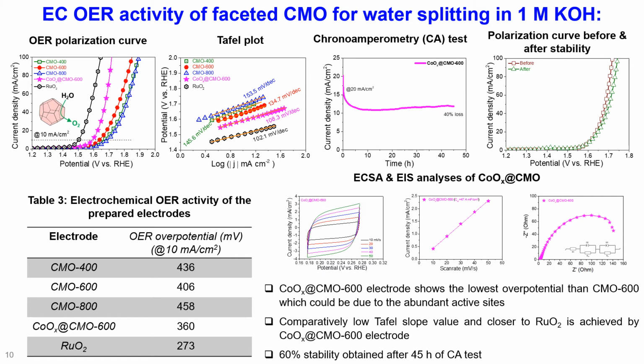Then the EIS analysis also shows a similar fitted circuit as before. So from this we can say that the CoOx coated CMO 600 electrode performed well for OER activity by providing the abundant number of active sites towards the water splitting process.